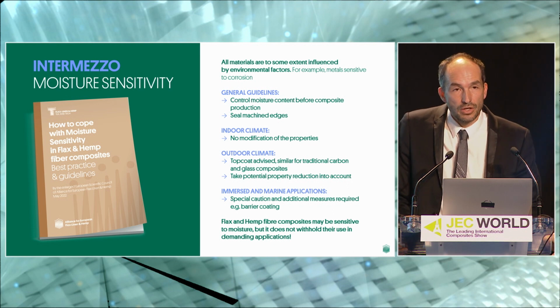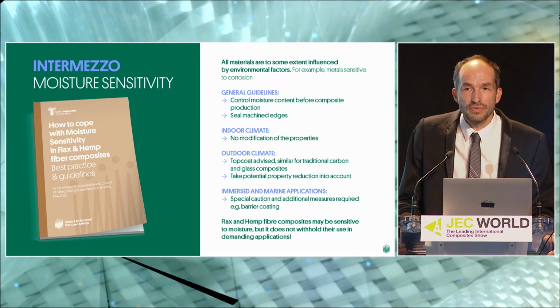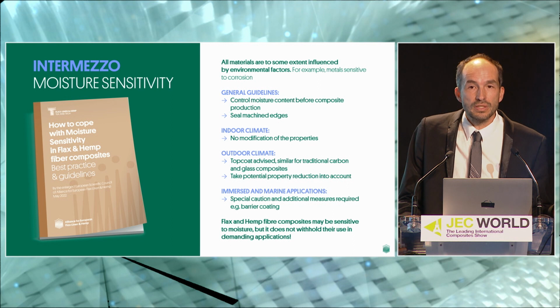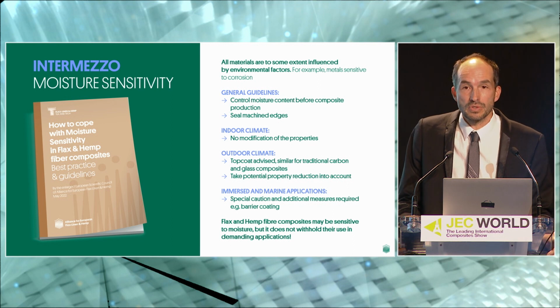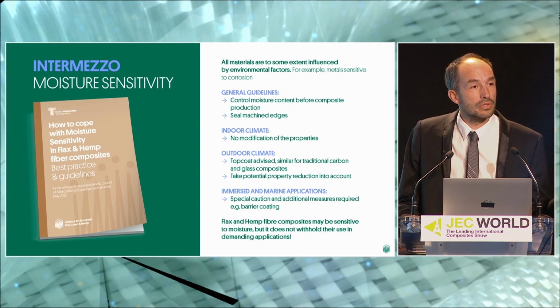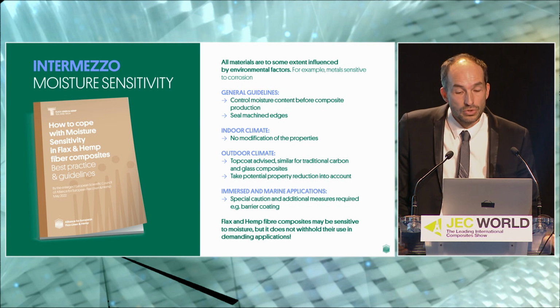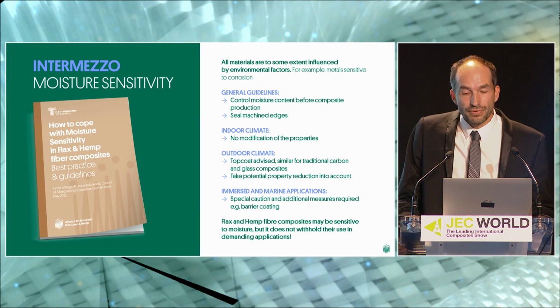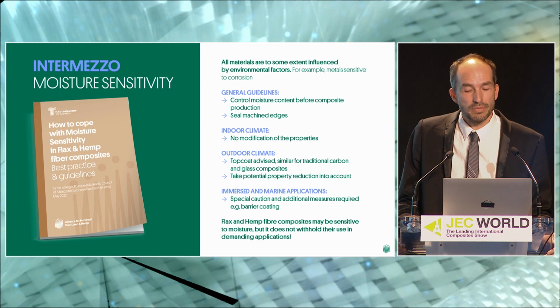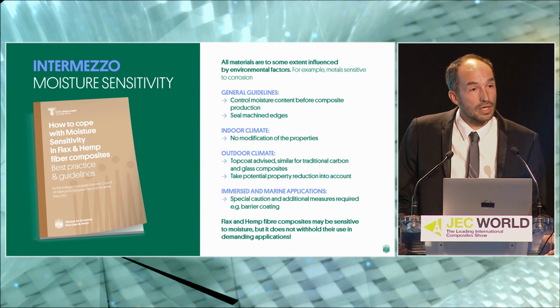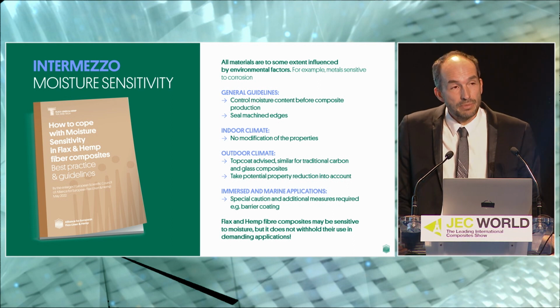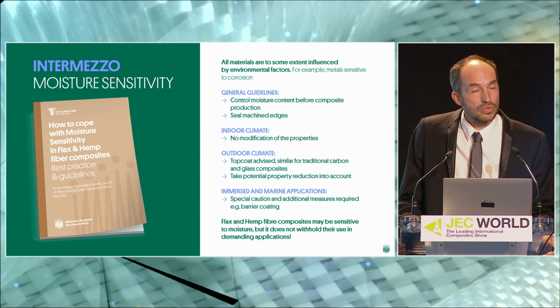exposed. And to cope with this moisture sensitivity, we proposed at first to discriminate the type of environment: indoor climate, outdoor climate, contact with liquid water, or immersion. And depending on the use, you can use different solutions. The general guidelines are at first to control moisture before the composite manufacturing, before the production of the composite parts, to seal the machined edges.